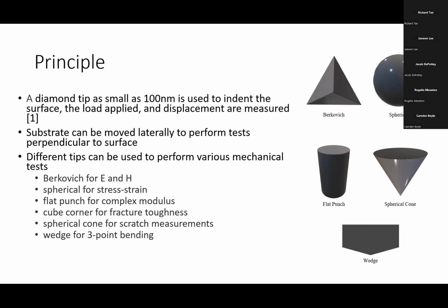Further on the principle, these nano indentations use a small diamond tip, which can be as small as 100 nanometers. That tip is then used to indent on the surface of your test sample. That indentation has an applied load, and that displacement is measured.